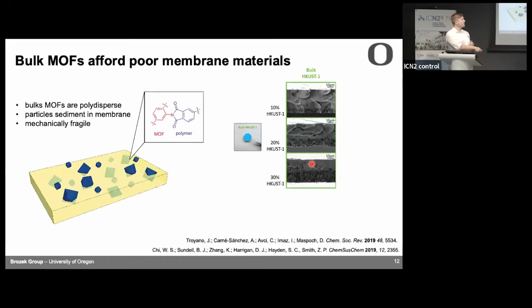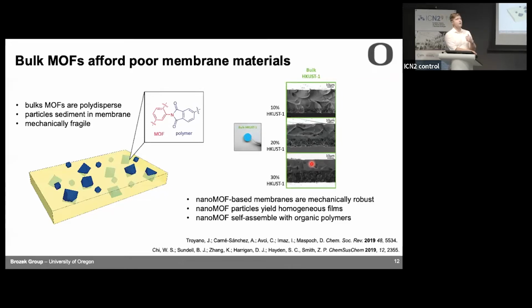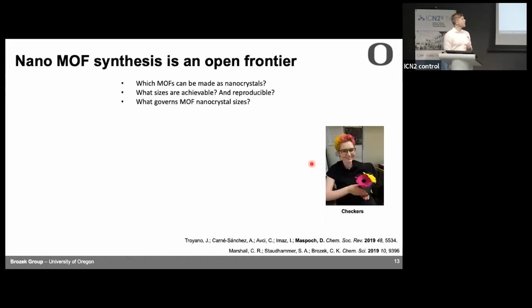A lot of really nice work has been pioneered by Daniel's group and others, Seth Cohen's group, Jeff Long's group, showing that if we can move towards MOF nanoparticles, you can get them to self-assemble, you can make membranes that are much more mechanically robust, and they should withstand those 8 atmospheres of pressure. But how to make MOF nanoparticles reproducibly of all these different MOFs that we know are out there is really still just beginning. And so my group came in trying to understand, for any MOF, how do we control the particle sizes and the morphologies? This is where my group first started working in this area.